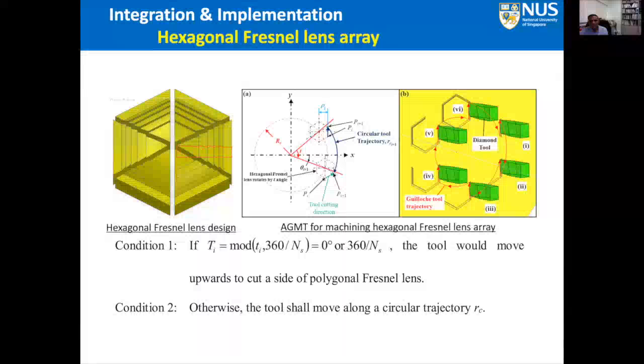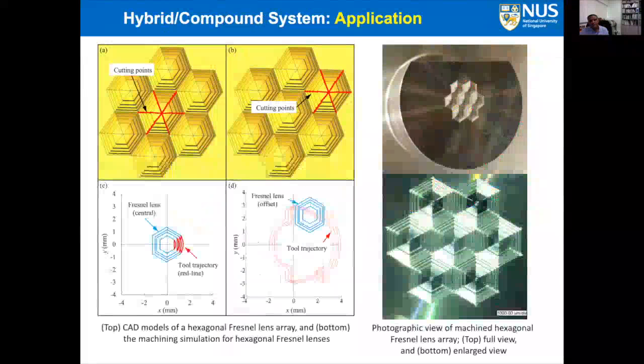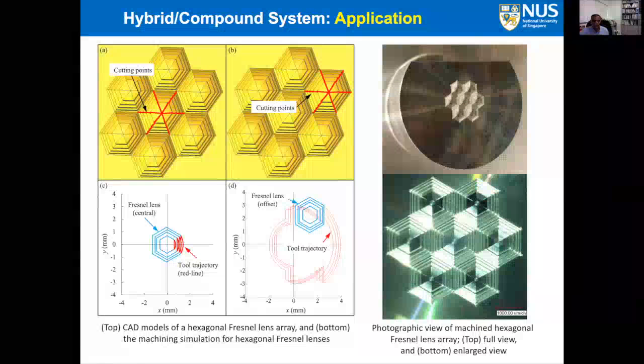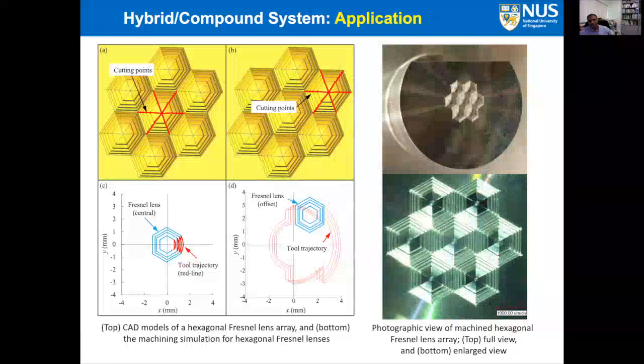So when we combine this, basically the most critical thing is the sharp corners. At these sharp corners, we have to negotiate them by actually rotating the diamond tool in relation to the surface that we want to machine. So what you see here is a combination of these multiple hexagonal Fresnel lenses. The successfully generated tool trajectories are actually shown here in this example.